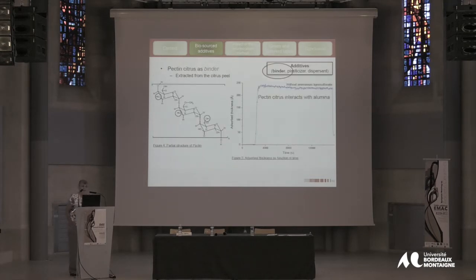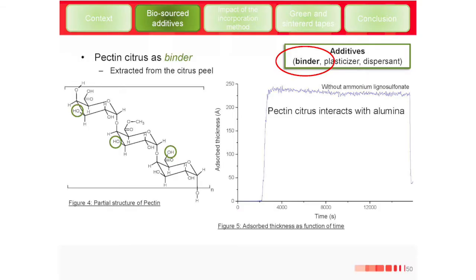Second additive is the binder. So we used citrus peel binder, okay? And how do we measure that a binder is adsorbed or not on a ceramic powder? We measured the thickness of the adsorbed layer by microbalance. And we have seen that the thickness of the adsorbed pectin layer is about 230 angstroms, so 23 nanometers.